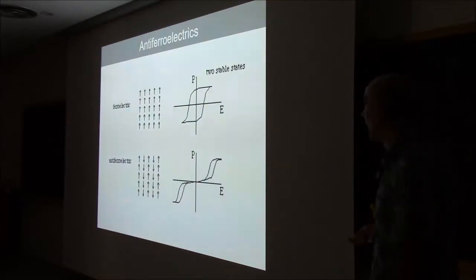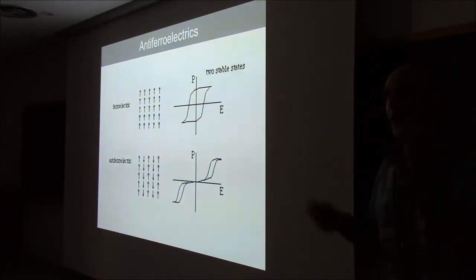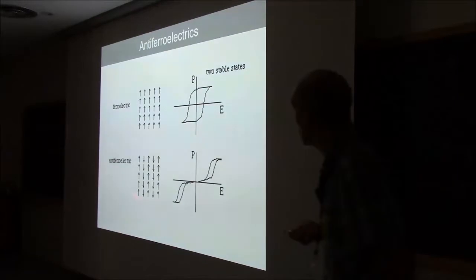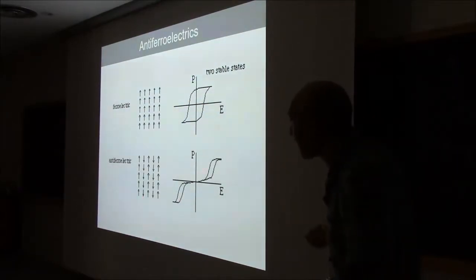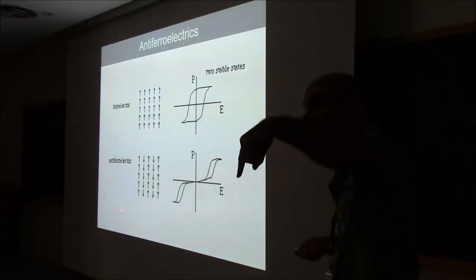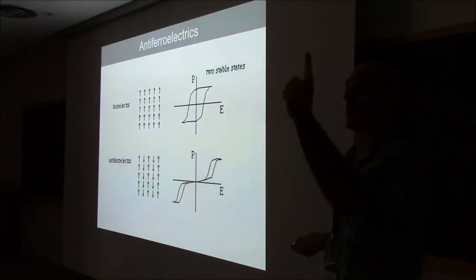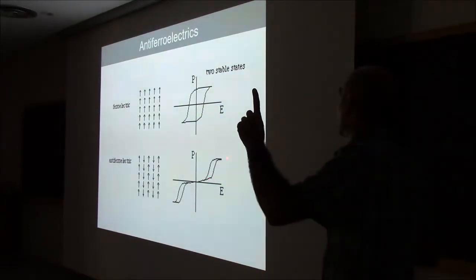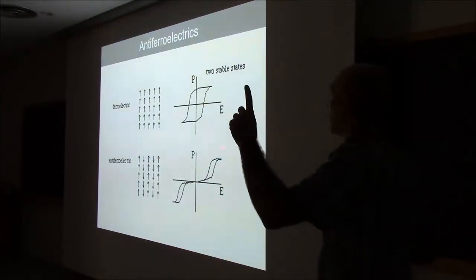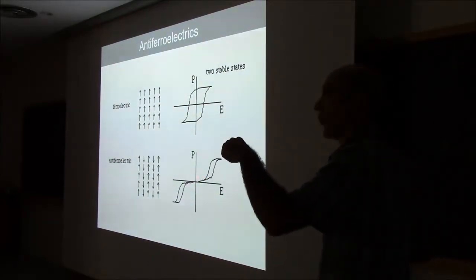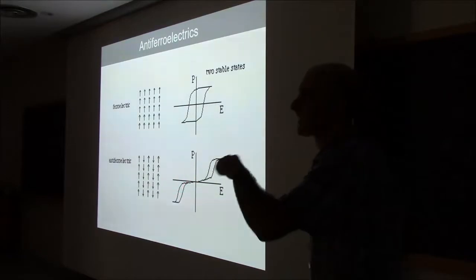And what's exciting about them is that if you apply a high enough electric field, say pointing up, you can destabilize this downward facing sublattice and make it point up. Then you reduce the electric field, it goes back to the antipolar state, so you have no permanent polarization, and then the same thing can happen if you point in the other direction. So you have double hysteresis.